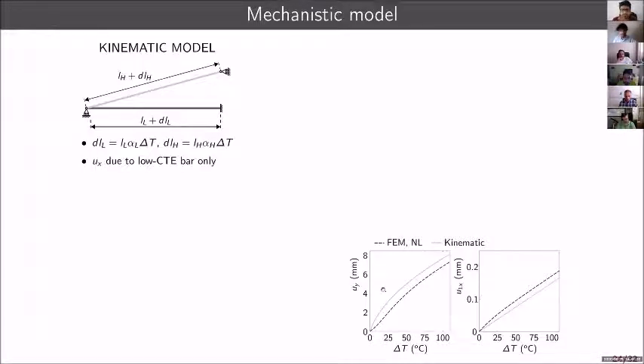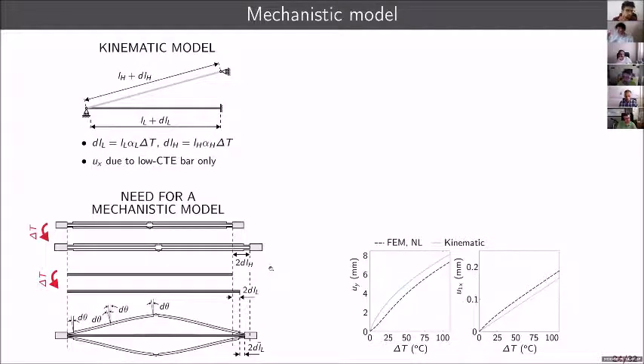The reason for this is because it misses a very important point, which is the following. I will try to explain it to you without looking at the graph. The high CTE frame actually wants to expand by a certain quantity, which is larger than the expansion of the low CTE bar. So if you consider them as standalone elements, once you put them together, the high CTE part will actually pull on the low CTE bar and cause some additional axial expansion that is not captured by the kinematics model.